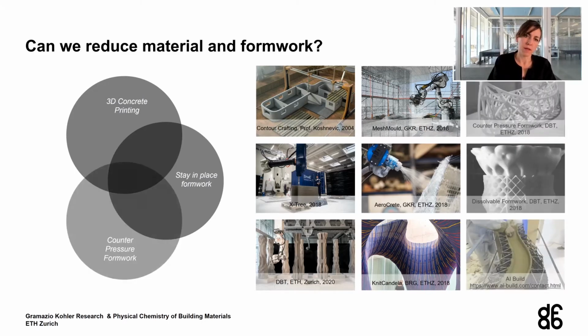A third avenue looks into 3D printed formworks that are very thin. However, to use such ultra-thin formworks requires an additional support structure around the shell, which is done using sand or additional printed structures around it to sustain the lateral pressure of the concrete inside. So these are all very valid ways of looking at how we can reduce material and formwork.